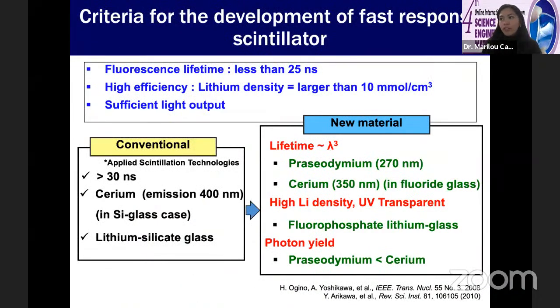So these are the three important material requirements: there should be a fluorescence or luminescence lifetime of less than 25 nanoseconds, so that the scintillator will have a response time of less than 25 nanoseconds. There should be a high lithium-6 density, typically greater than 10 millimole per cubic centimeter. And of course, the light output of the scintillator should be high enough so that it can be detected by photomultiplier tubes. So the conventional lithium-6 scintillator, which is based on cerium-doped lithium silicate glass that's emitting at 400 nanometers, has a luminescence decay time that is greater than 30 nanoseconds. So obviously, it's not enough to use for detecting the scattered neutrons.